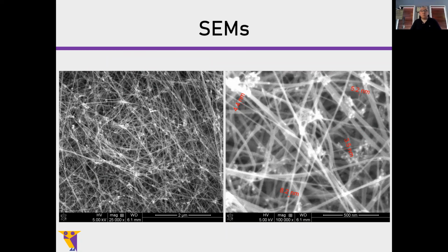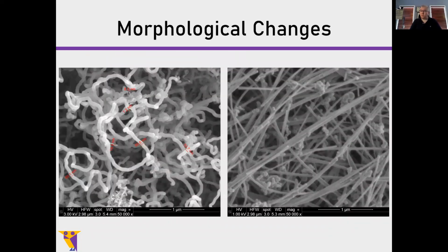But one of the problems with making nanotubes is that small changes in reaction conditions and fuel formulations can create huge morphological changes. I refer to this as the pasta model. What you saw before was capellini. On the left, you see ramen, and on the right, you see linguine. Small changes in reactor conditions in terms of altering fuel ratios, changing methane to ferrocene concentrations, altering pressures slightly, will create these variants. Why? I don't know. Needs to be studied.